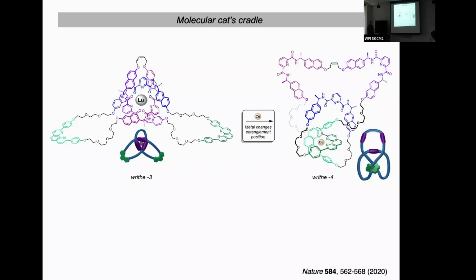The student who was doing it made the trefoil knot with just lutetium templation. They took the NMR spectra of the crude material, could see that it was this lovely lutetium coordinated knot, and then they columned it on our gel permeation chromatography unit, and the person who'd been using it before them had been chromatographing, purifying a compound that had got some copper in it, and there were some copper residues on the column. And when the knot came off the column, the NMR spectrum looked completely different. And when we did mass spectrometry, we saw there was no longer any lutetium in the knot, there was copper. And the copper had displaced the lutetium.